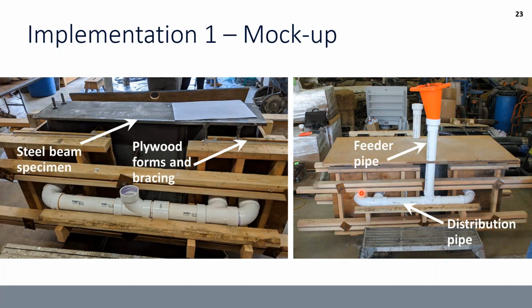So this top sheet of plywood is there to simulate the bridge deck, and we have this inverted cone. I know, Mike, you have a good word for it. It's a UHPC placement device or something. Worked incredibly well for the casting of UHPC. So they were able to just pass up those kind of 5-gallon pails, pour it into the inverted cone, and that pressure head was enough to fill all of the forms.